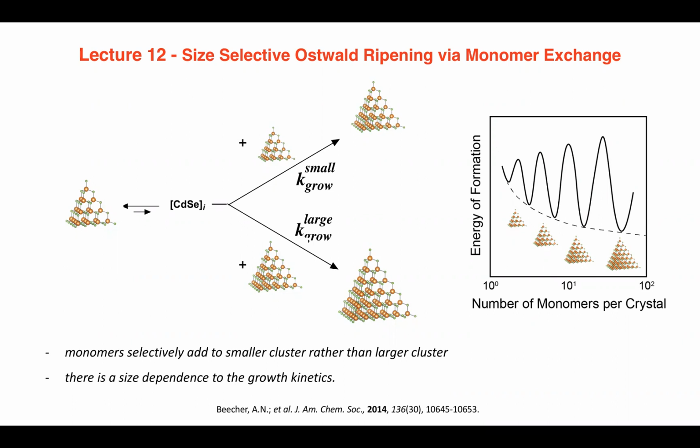There's a barrier. It's a chemically challenging reaction. A lot of these crystals are made in the bulk at much higher temperatures than what we're growing them at in solution. If we're working at very low temperatures in solution, it's possible to make little crystallites. And if you want to make a bigger crystal, you've got to go up to the temperature at which the bulk is grown. So the higher you go, the easier it is to make a bigger and bigger thing.